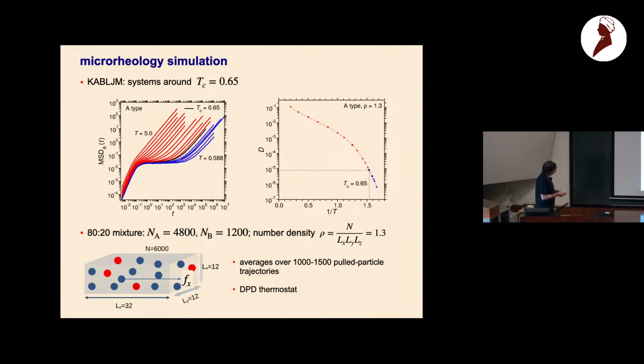So we use this geometry and apply the microrheology. We just take a single particle and pull it through the system via a constant force Fx in the x direction. In order to get a reasonable statistic, we have to take averages over the order of 1,000 to 1,500 trajectories, and again we use a DPD thermostat in this case.